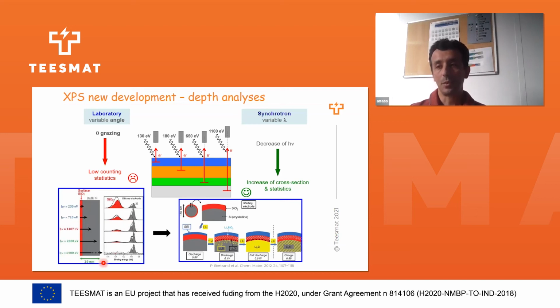And in this way, when we form the SEI, we can follow the thickness and the composition of the SEI at different states of charge, without any sample preparation or etching. So this is another way to probe deeper and evaluate the thickness and the composition of the SEI using modulated photon energy.